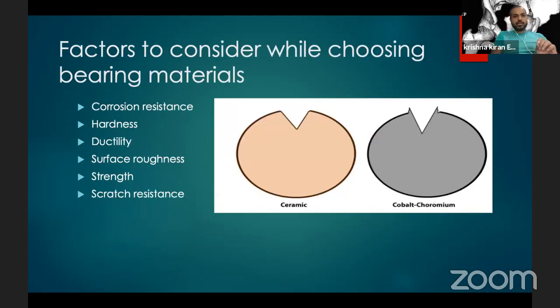So the factors to consider while choosing bearing materials: you must choose the bearing material with the best corrosion resistance, hardness, ductility, surface roughness, strength, and scratch resistance. So here ceramic scores over cobalt chrome. If you have a scratch on ceramic, it will be like a trough there. But if you have a scratch on a cobalt chrome head, you will have 2 peaks and a trough. So the asperities and the surface roughness will increase, thereby increasing the abrasive wear of this material. So currently, the standard of care is to use a ceramic head wherever it is possible.